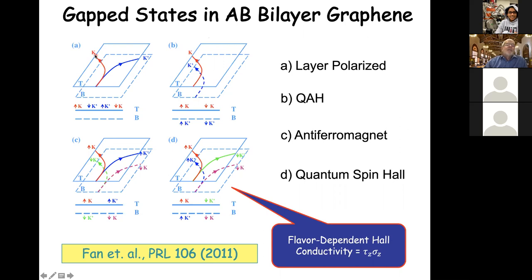And these arrows are representing the chirality of the system, the sign of the Hall effect. And what these two arrows are emphasizing is that because these valleys are related by time reversal, when they have the same sense of polarization, they have opposite Hall conductivity. So this layer polarized state A in bilayer graphene has no net Hall conductivity, but there are many other states nearby in energy that either have spin Hall effects or even an overall Hall effect if opposite valleys have opposite sense of layer polarization. Then you get a quantum anomalous Hall effect. So this is the story of AB bilayer graphene.